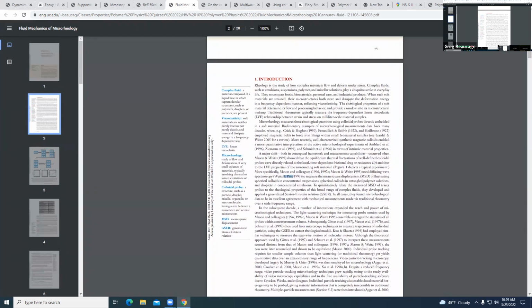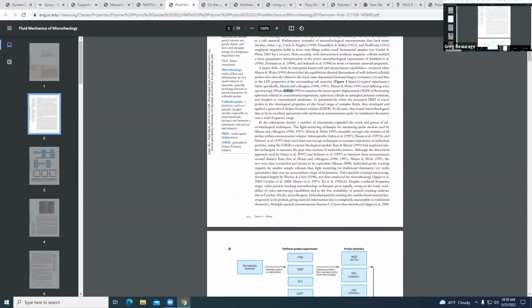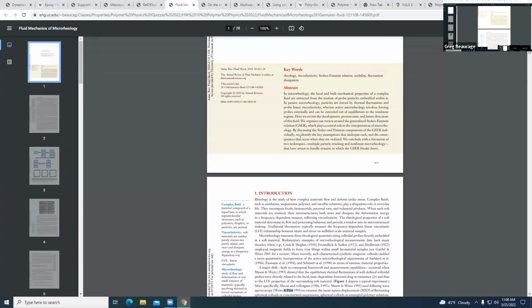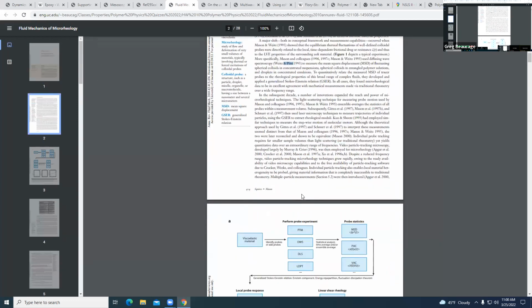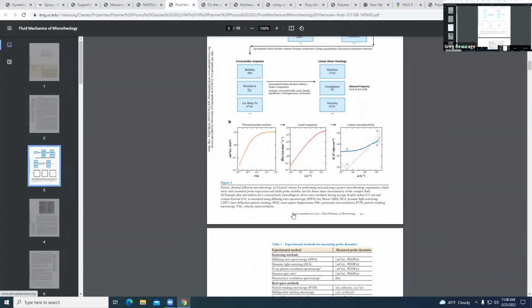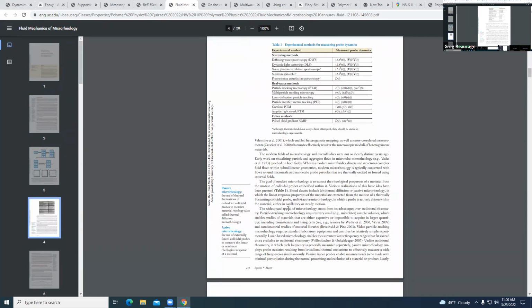At the time, people thought it was nothing important, for the most part, until they realized that the measurement could line up exactly with mechanical rheology, like they fall on top of each other, and they can access these really high frequencies where the mechanical doesn't work anymore. So then all of a sudden that became important. Then they realized you can do this with X-rays and neutrons. So it becomes more and more important. And it's a pretty powerful technique given that it seems like a stupid idea, you know.